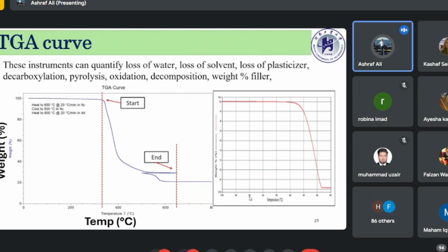So look toward this TGA curve. At the first stage, we have increased the temperature up to 200 degrees C. There is no change, there is no weight loss, and the weight is almost 100%. The curve is just a horizontal line. Now up to about 380 degrees C, there is no change. And at 390 degrees C, the weight loss starts, and the curve is dropping down. The weight of the sample is decreased.